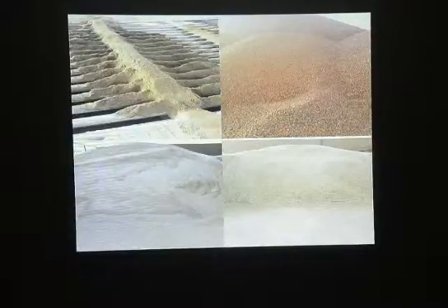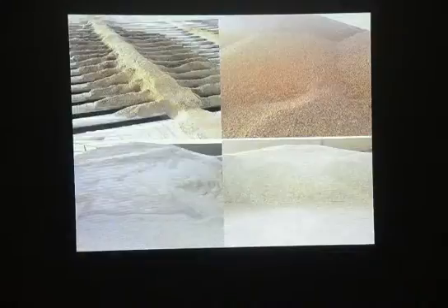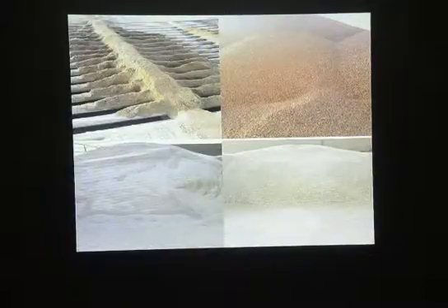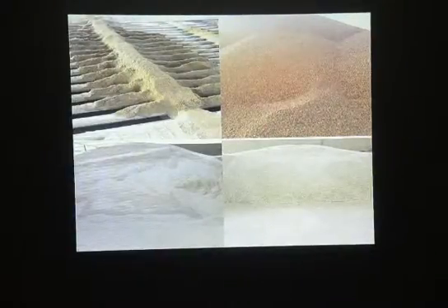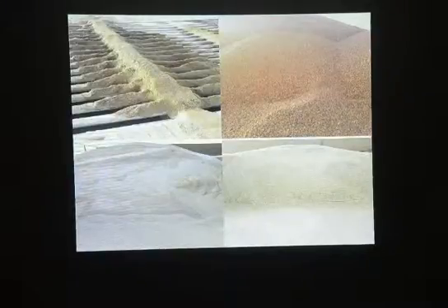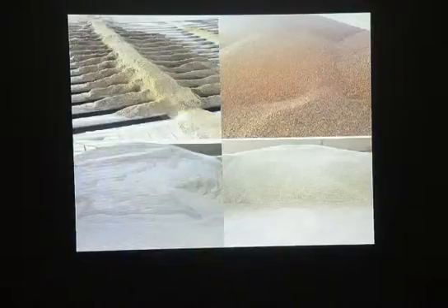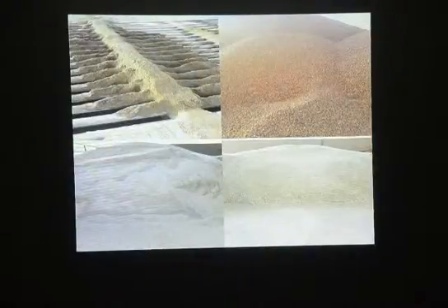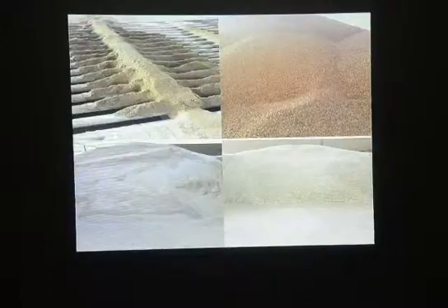Well, something has to give it more densifying to be more dense, and that's why there are different sizes of aggregate. We don't always use the same size aggregate. I mentioned number 5 earlier, but depending upon what plant I'm in, I've also seen a number 8, which is a smaller size. So yes, you're right, there are different densities of block. Good question. Did I answer your question, sir? Yes. Thank you.